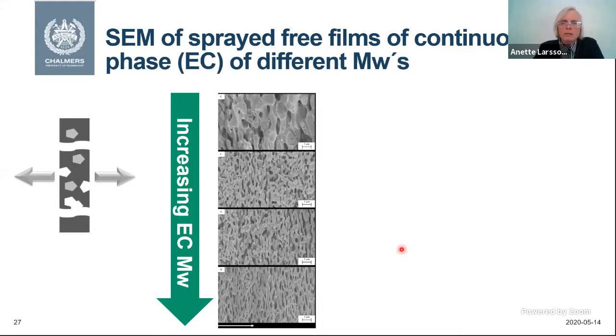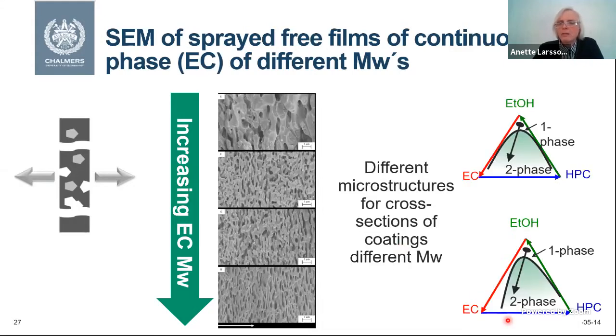And then we can explain that by the two-phase things, that the shape of the phase diagram changes depending on the molecular weight, but also that higher molecular weight will give higher viscosity, which locks the system when less ethanol has evaporated, meaning that the occurrence of the phase separation has been stopped earlier.